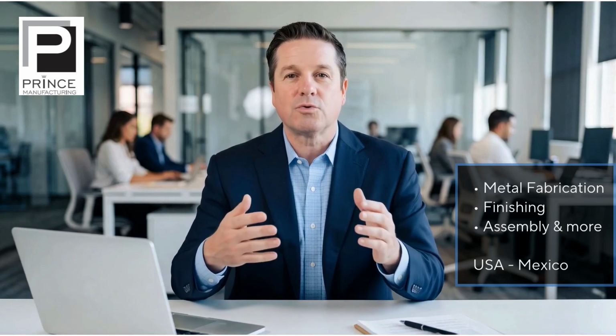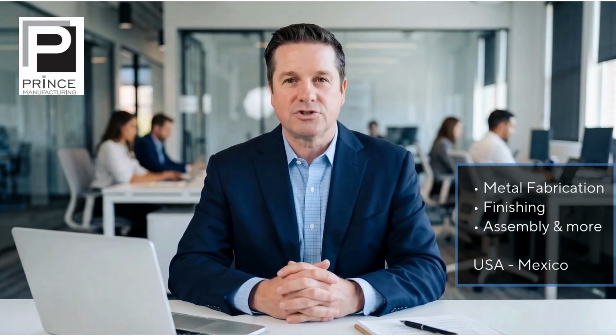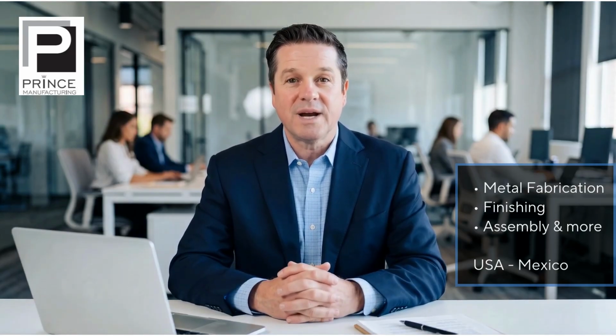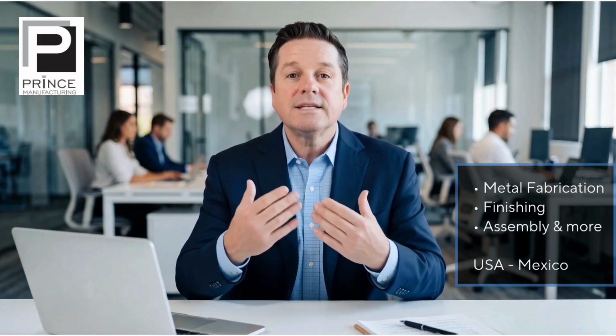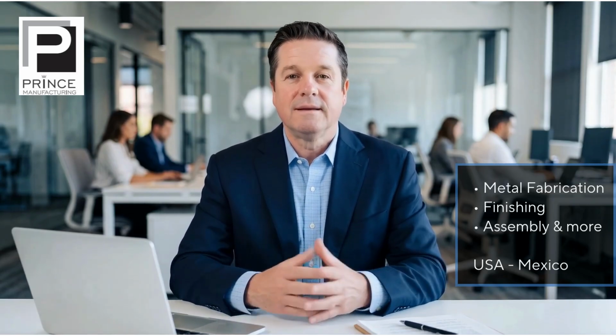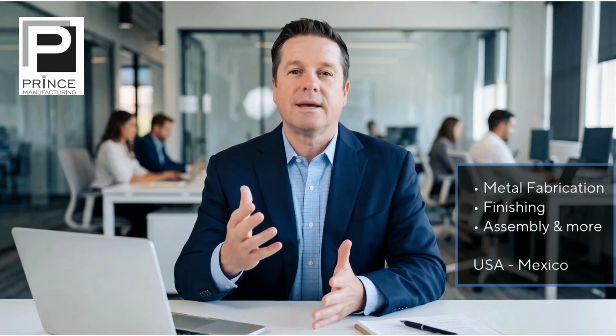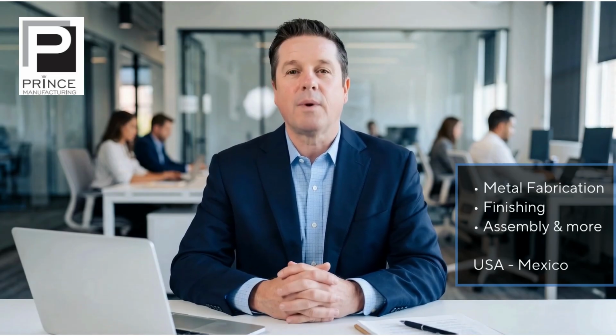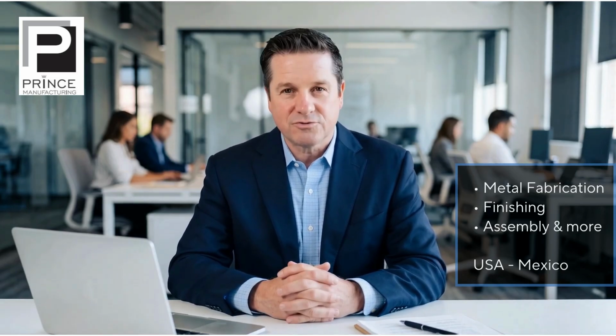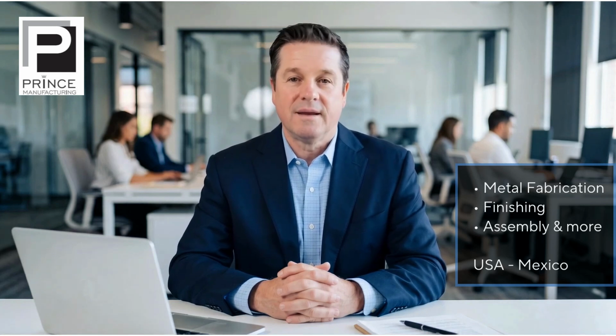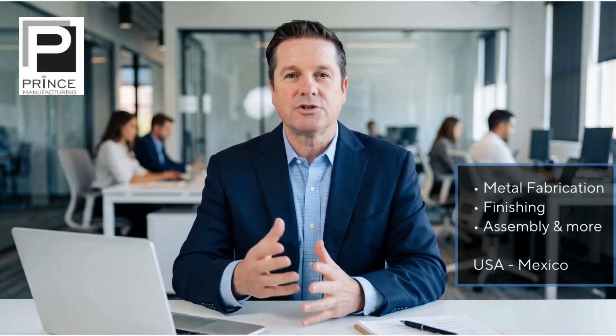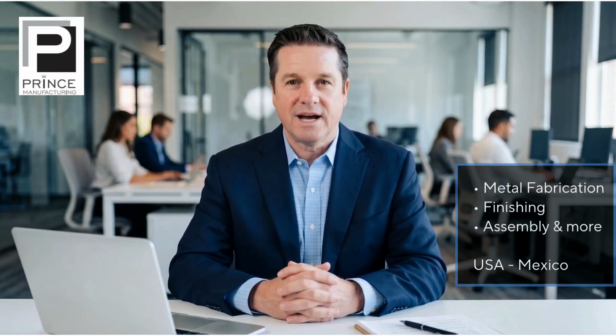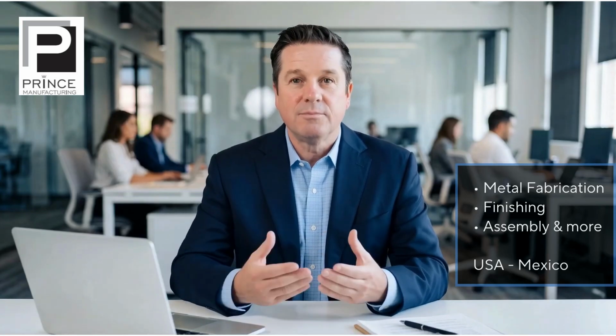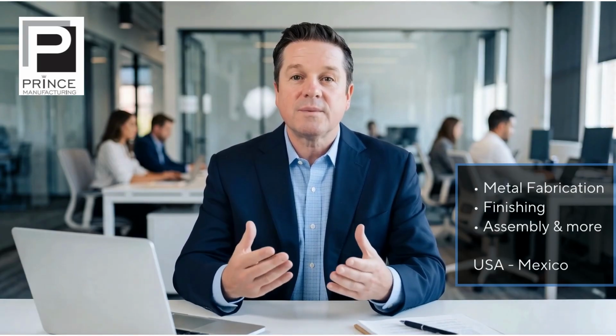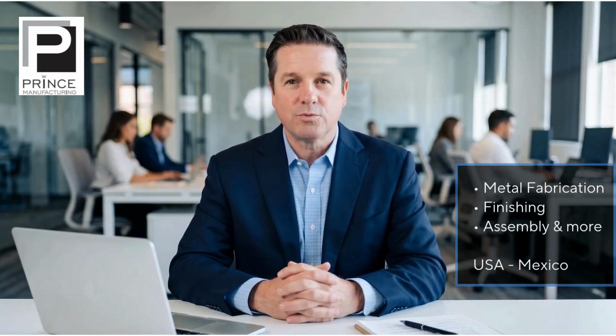Plating is often a strong choice when a component requires a relatively thin and controlled finish. Examples include fasteners, stampings, brackets, electrical hardware, connectors, and other components with dimensional requirements. But plating thickness is not perfectly uniform across every geometry. Edges and projections may receive more deposit. Deep recesses and shielded areas may receive less. Blind holes, welded seams, overlapping surfaces, and complex cavities can affect cleaning, rinsing, plating distribution, and drainage. Racking also matters because the component needs reliable electrical contact during the process. The correct plating system therefore depends on the material, geometry, tolerances, volume, and performance requirements.